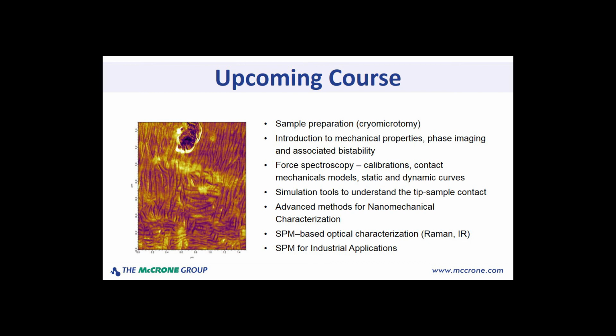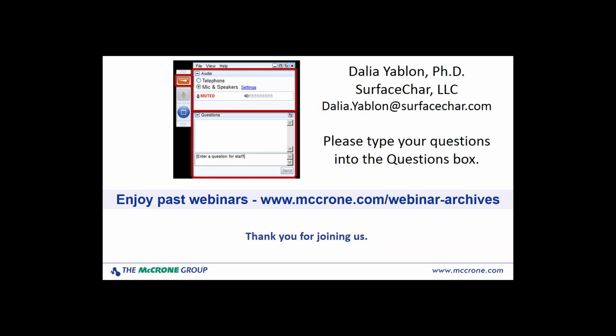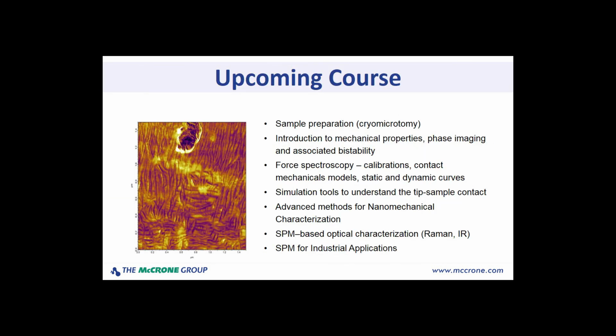However, you can use heated probes, which is another kind of thermal measurement I did not mention. So you can have these probes that you heat, and then you have localized heating just at the point of the probe. That is useful for measuring thermal transitions like Tg, or glass transition, or melting types of transitions right at the point below your probe. And that is heating from the sample, not from the substrate. So that would be a better approach to separate your sample from the substrate.